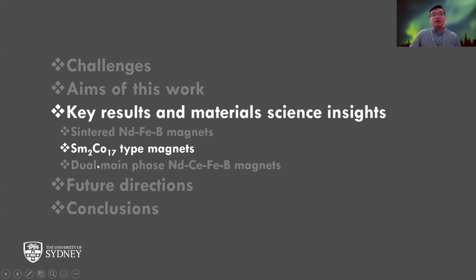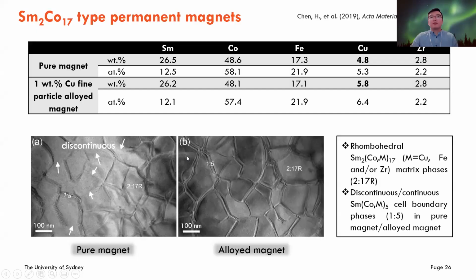And for the second part, the samarium cobalt type magnets are actually a totally different type of permanent magnet. The coercivity here is majorly governed by so-called domain wall pinning, where you can see the cell boundary here. When the domain wants to penetrate and go through this part, it actually pins on this boundary on some feature. And the pinning force here is proportional to the coercivity.